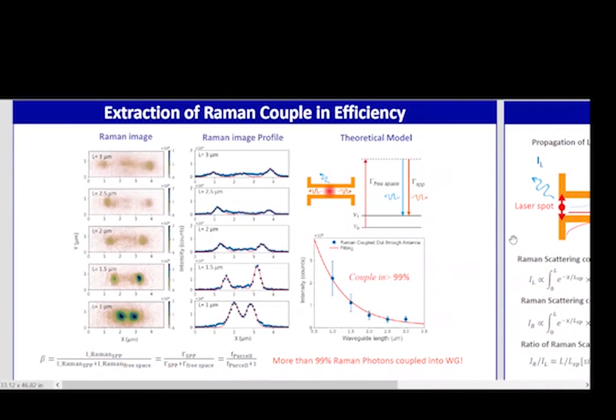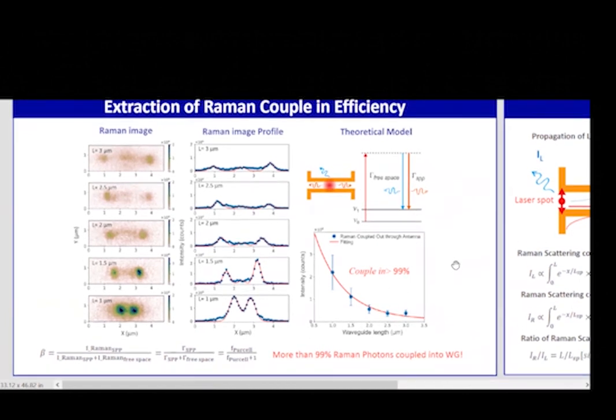And finally, by measuring the Raman scattering which was coupled to free space and which was coupled to the waveguide, we precisely determined that more than 99% of the Raman scattering photons will be coupled into the waveguide instead of going to free space. Which means here we can offer a unique way to achieve unidirectional scattering of the Raman scattering.